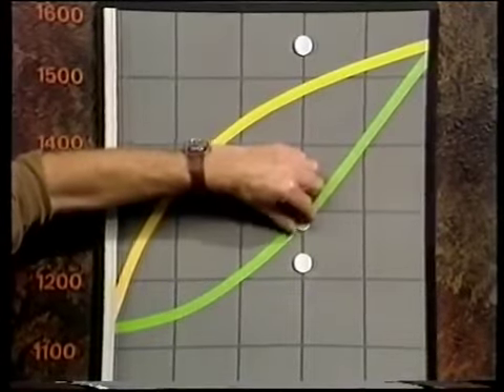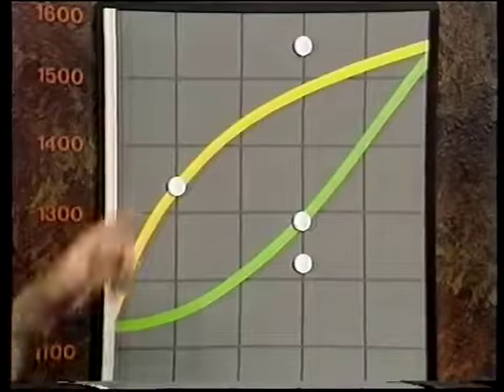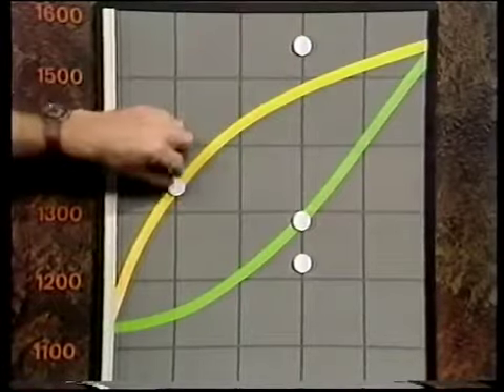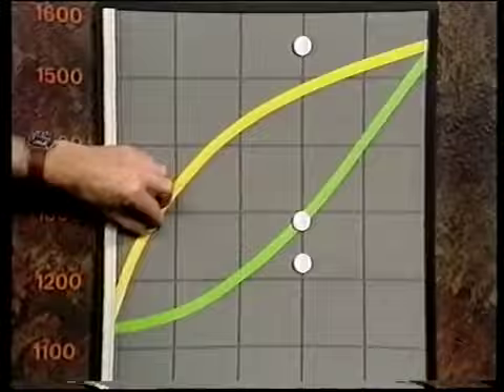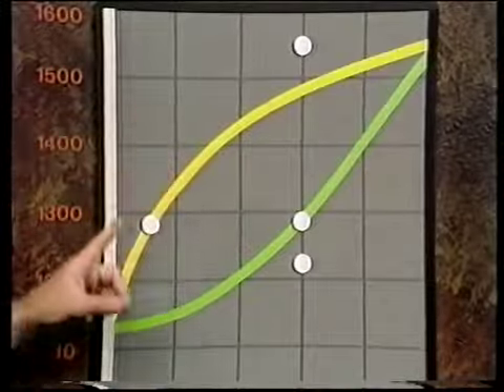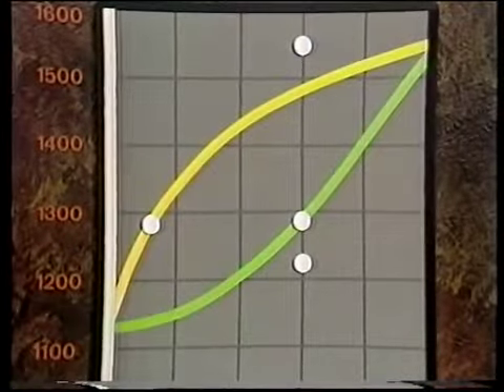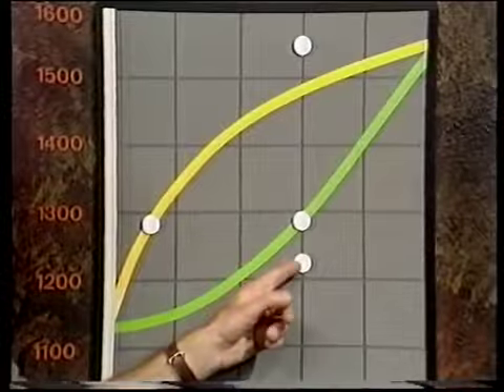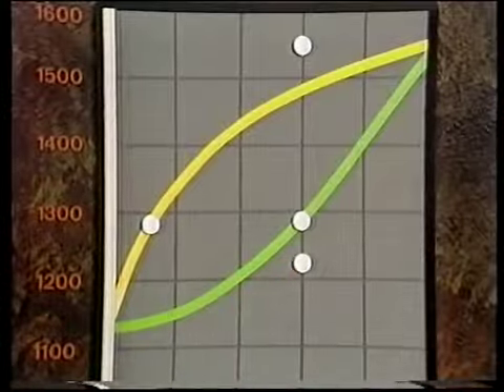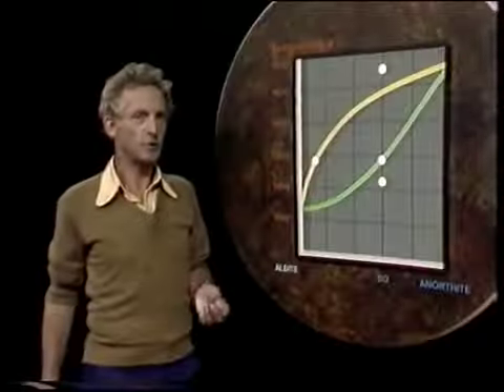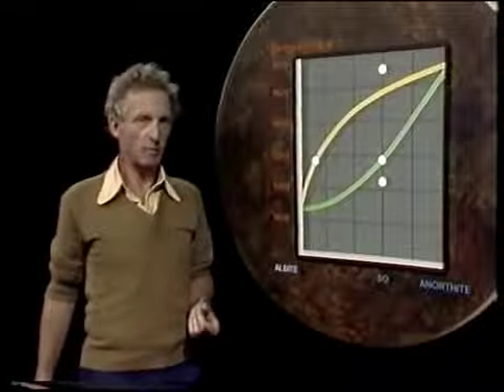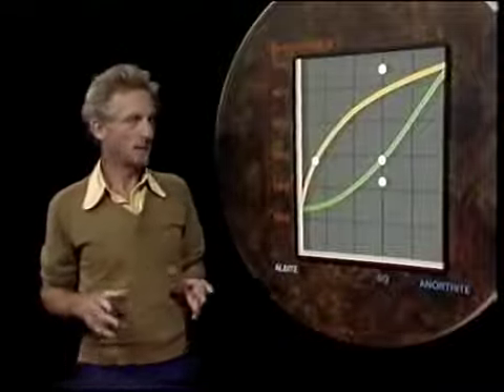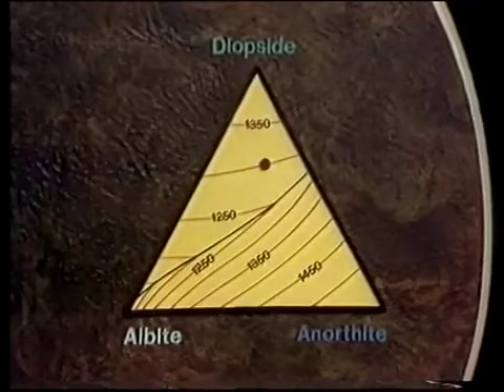It's got to stop where the composition of the solid reaches the composition of the melt you started with. And at that temperature, the last few drops of liquid remaining plot there on the liquidus, very rich in albite. And your final solid will be made up of homogeneous crystals, solid solutions that consist of 60% anorthite, 40% albite, but only if cooling has been slow enough for equilibrium to be maintained.